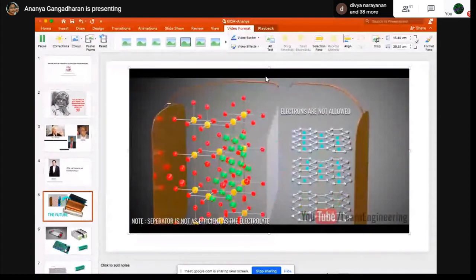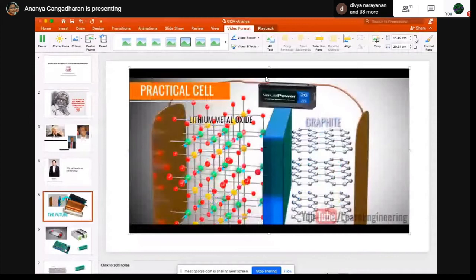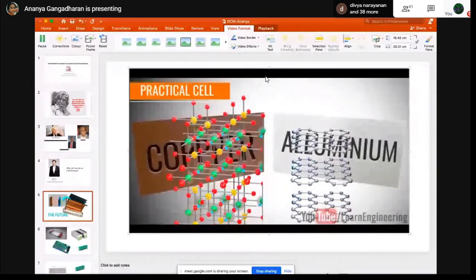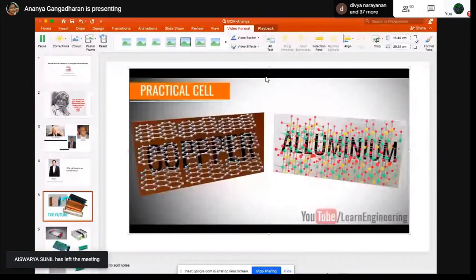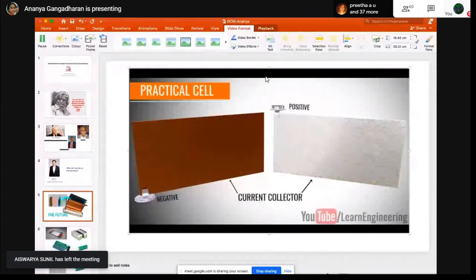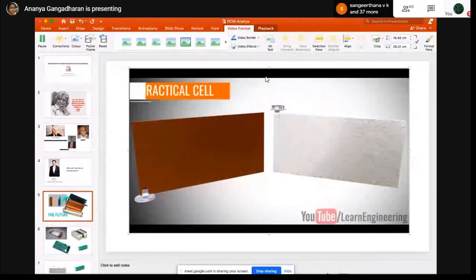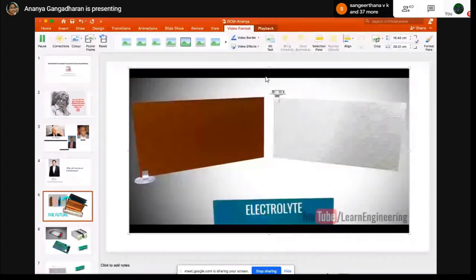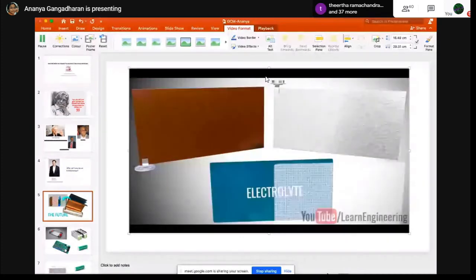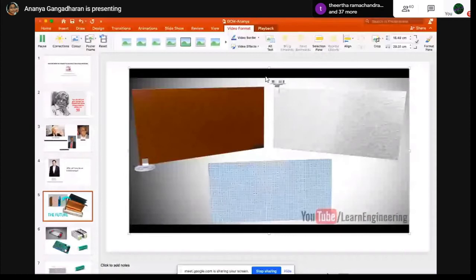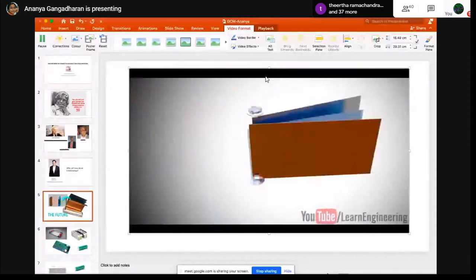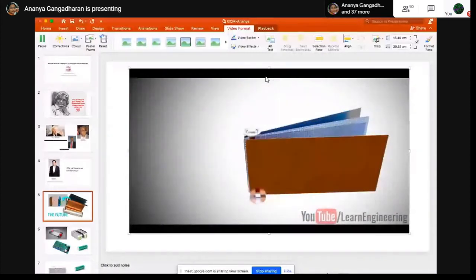In a practical cell, the graphite and metal oxide are coated onto copper and aluminum foils. The foils act as current collectors here, and the positive and negative tabs can be easily taken out from the current collectors. An organic salt of lithium acts as the electrolyte, and it is coated onto the separator sheet. All these three sheets are wound onto the cylinder around a central steel core, thus making the cell more compact.